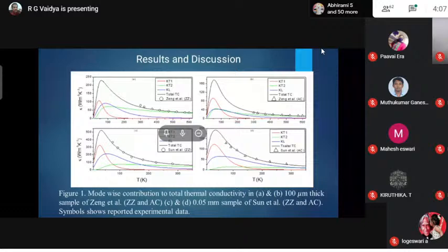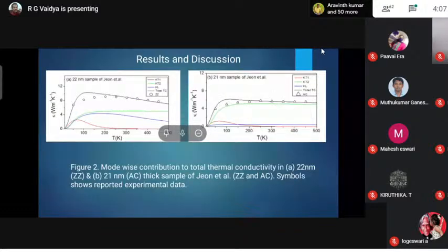Our calculation indicates that the experimental results are in agreement with our calculations, and it is observed that transverse phonon contribution is more in black phosphorus along zigzag and armchair direction. This figure indicates the nanoscale black phosphorus samples. Here it is clearly observed that longitudinal phonon contribution is very less in armchair direction, whereas in the zigzag direction, both transverse and longitudinal phonons contribute equally.